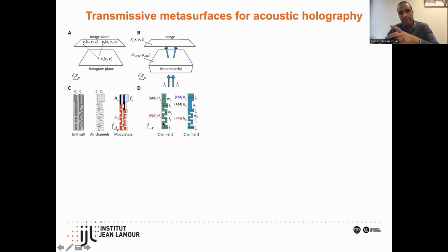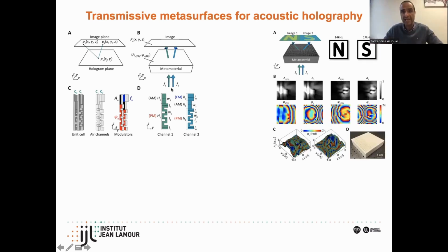And it's a little bit complex, because it's very sensitive to the geometrical parameters. You can see here PM. We can modulate the phase with the labyrinthine structure with different parameters. AM, amplitude, we can use the H1, the height of the cavities, and of course the FM, which is the frequency modulation. Also, it depends on the geometrical parameters of this modulator. So I will not go into the details. Here you have the numerical and experimental results.